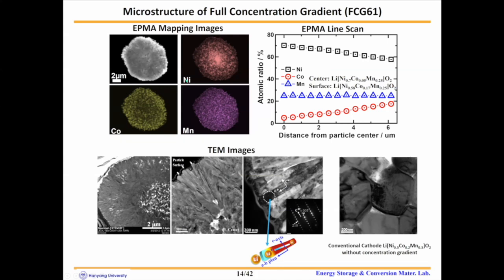This is the microstructure of the full concentration gradient material. As you can see in the EPMA mapping image, the nickel was depleted at the particle surface and gradually increased toward the particle centers. EPMA line scan also verified successful synthesis of the FCG cathode active materials. And as you can see from the TEM images, surprisingly, the FCG cathode particle is composed of long rod shaped primary particles aligned toward the particle centers.